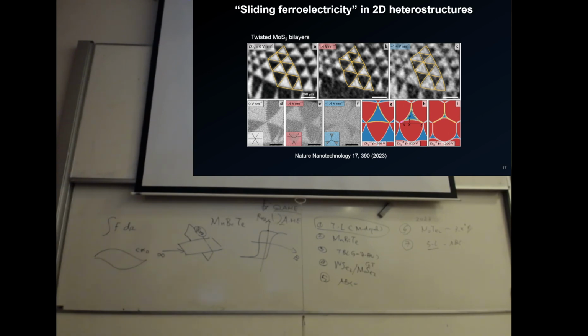For example, there's a paper coming out in 2023, and people have done some measurements locally on this Moiré pattern by just changing this vertical electrical field from positive 1.4 to negative 1.4 volt per nanometer, which is a large number actually. 1 volt per nanometer is huge. This goes to gigavolts per meter, right?